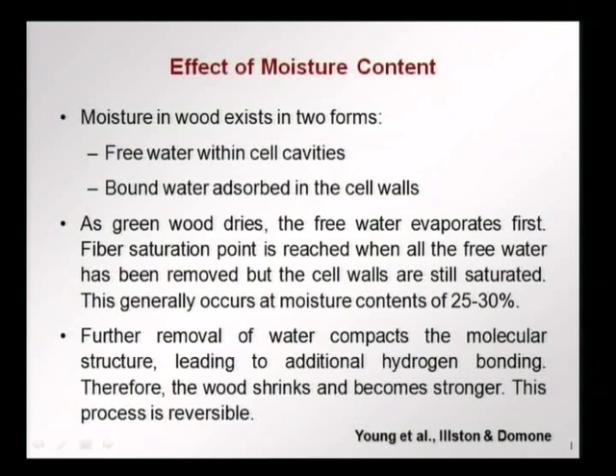and we reach a certain point called the fiber saturation point, where all the free water has been removed, but the cell walls are still saturated. We have removed all the water from the interior of the cells, but the walls themselves are still saturated with water. This generally occurs at moisture contents of about 25 to 30%, that is called the fiber saturation point. Until that point in time, the properties do not change much and there is not much shrinkage when you are removing the free water.